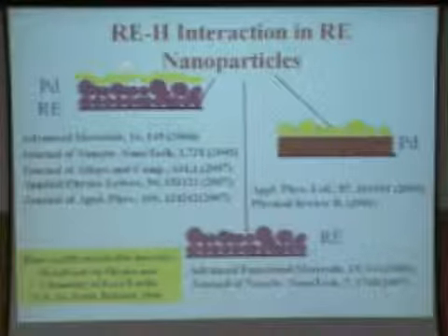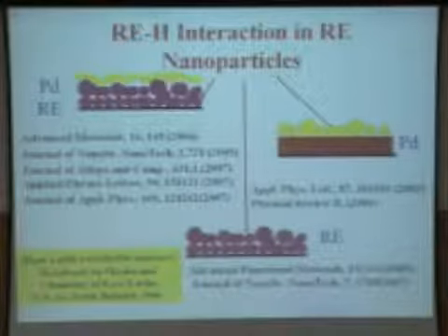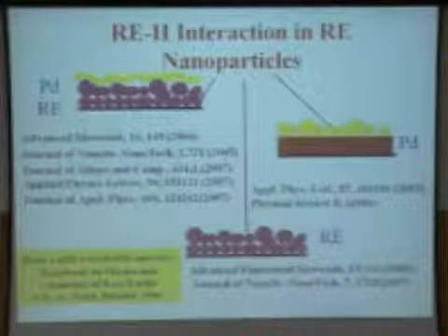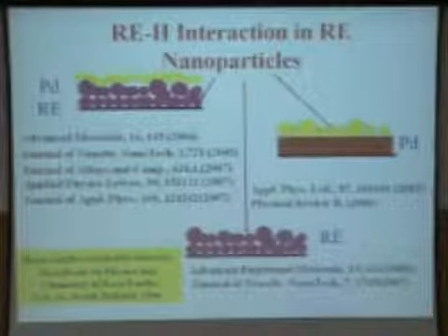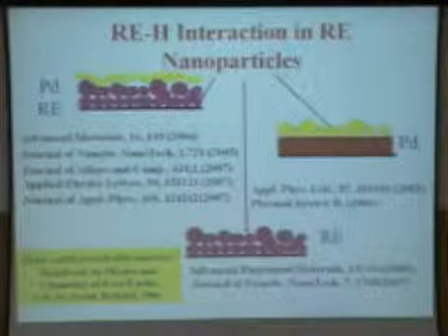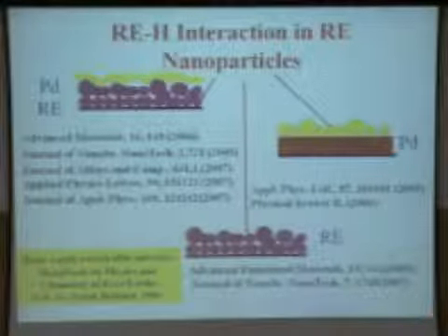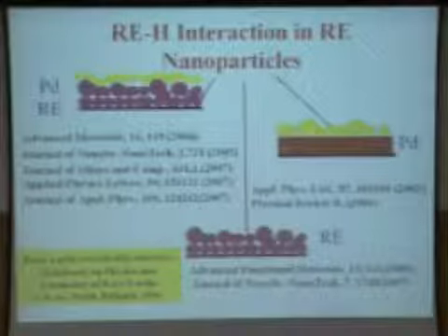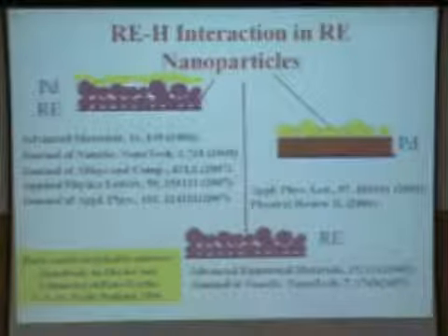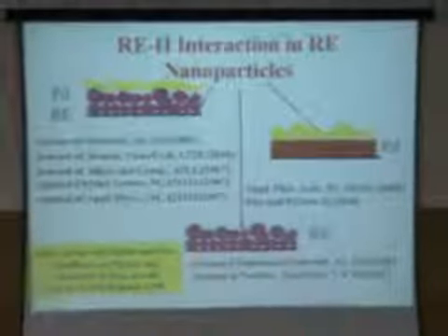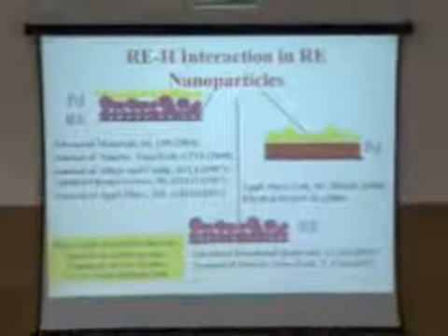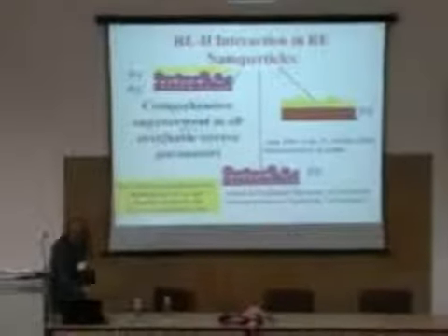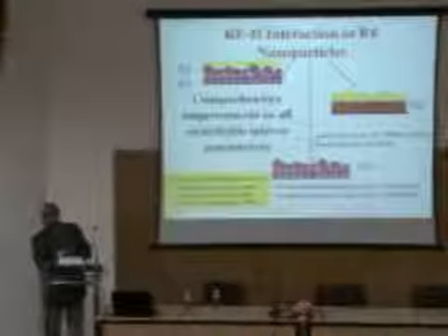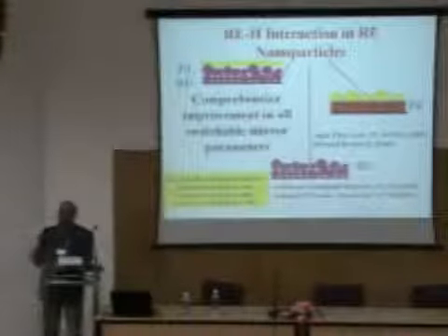The first system is a simple structure of what I described earlier: a thin film of rare earth material protected by a palladium overlayer. The only thing we changed was that we modified the thin film of rare earth material, using an extremely simple technique which I will describe later, and changed the thin film to a nanocrystalline layer. We kept the palladium overlayer as it is. What we found was a comprehensive improvement in all the switchable mirror parameters which I described. All of them improved. We just made a small modification in our synthesis, and there was a tremendous improvement in all these switchable mirror parameters.